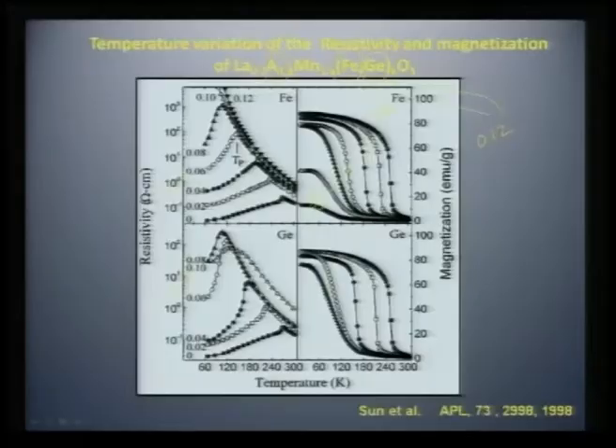Practically it goes very weakly ferromagnetic, and the same situation is there when you look at the resistivity versus temperature function. As you increase the iron concentration to 12%, it completely transforms into an insulator. Same situation for germanium. As you substitute, you see the TC decreasing, and you see the resistance going almost to an insulating stage.